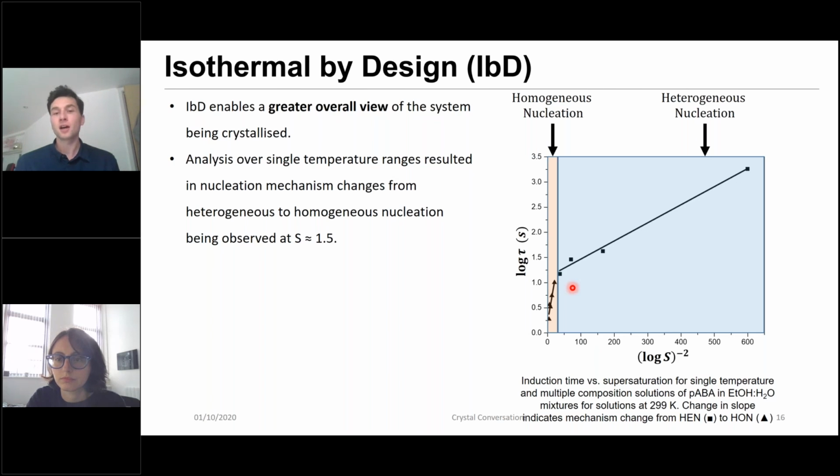I would imagine when you get to the higher supersaturation, when the driving force is high enough, you get something quite similar, but it depends on the solubility differences. We're calculating supersaturation based on the solubility known over the range of compositions. So changing the anti-solvent, you have to know the solubility over the full range, and so that might alter it, definitely.